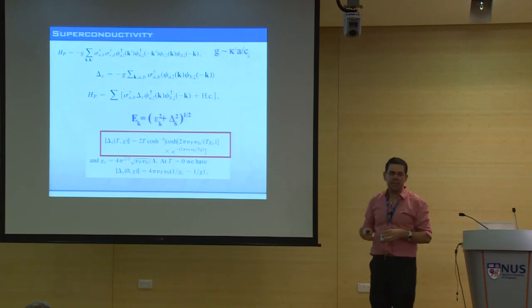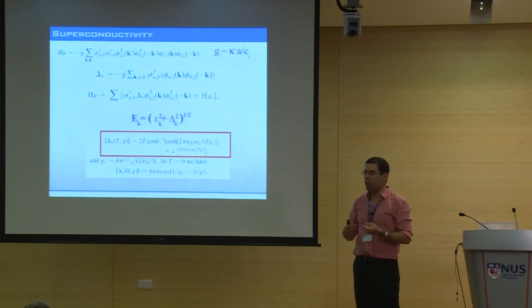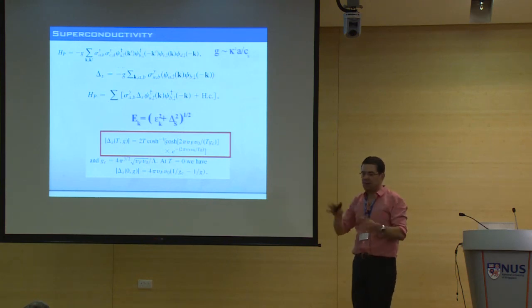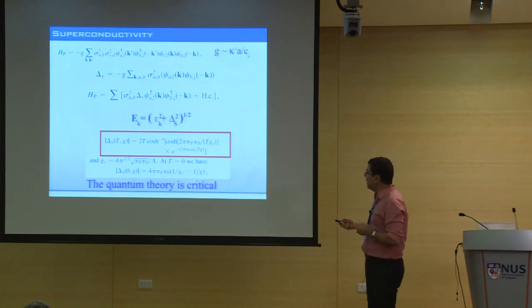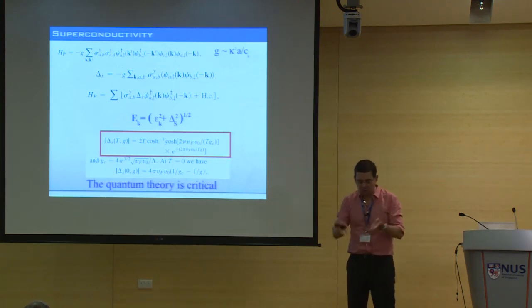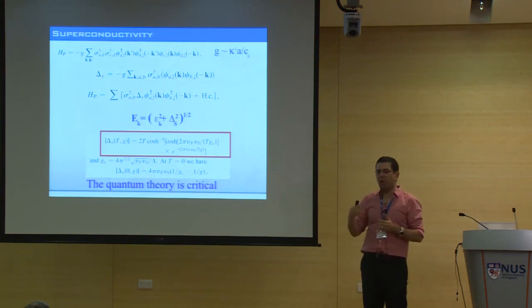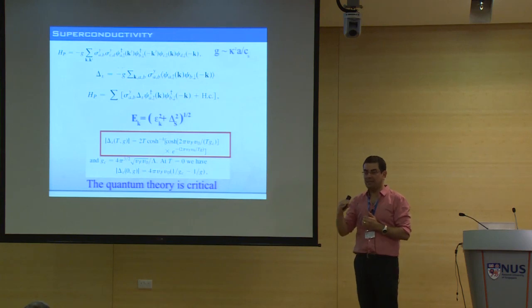So to get superconductivity, you need these Dirac particles to pair. Okay? They have to form Cooper pairs. I'm not going into the detail of this theory, so you can solve the traditional BCS problem for Dirac electrons. And what you find, which is interesting, is the following: because you have a suppressed density of states, superconductivity can only exist above a certain electron-phonon coupling. Below it, it cannot exist. This is not what happens in BCS, in normal metals.